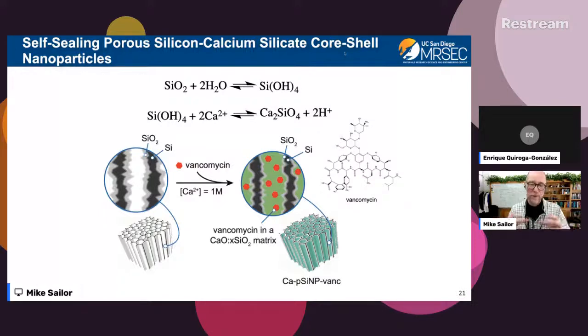So you basically locally generate cement inside that very, very small nanometer scale structure. Again, these nanoparticles are really nanoparticles. They're on the order of 100 to 200 nanometers in size. So this reaction is very localized in a water solution, and it's very focused on just our silicon nanostructure. If we do this chemistry right, we end up with particles that have a very simple sealed drug sitting inside the nanoparticle. I'll show some examples of that here in a few minutes.